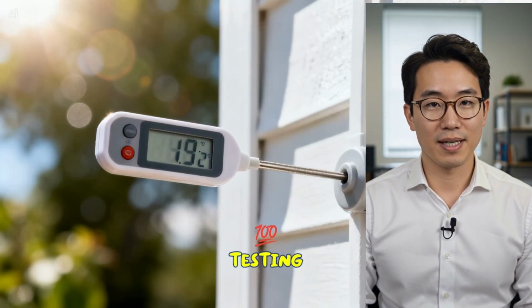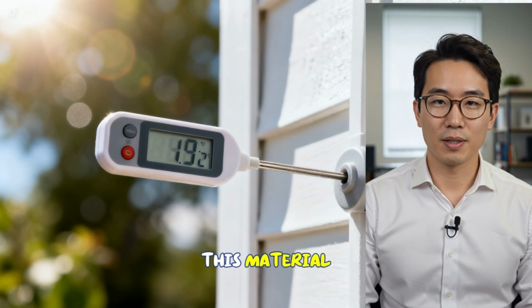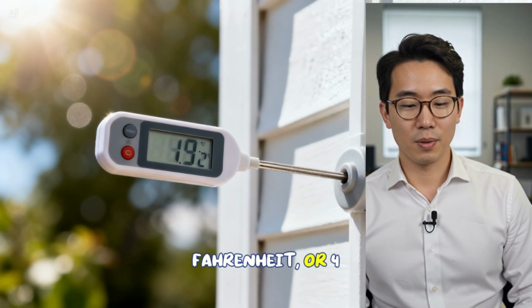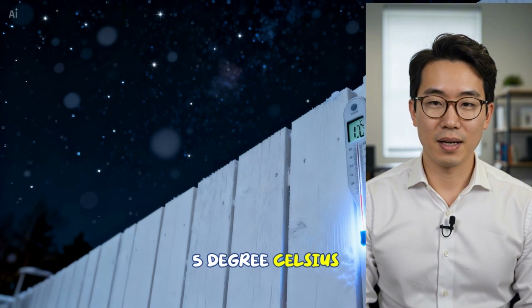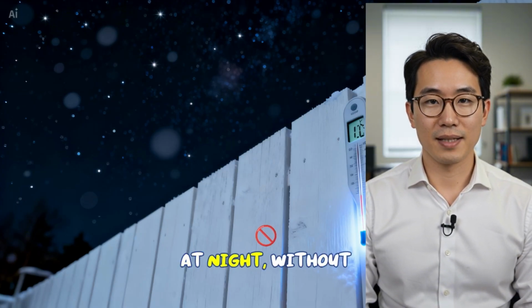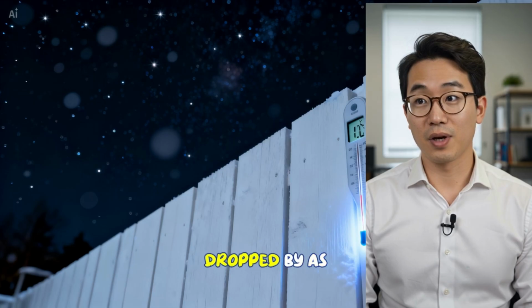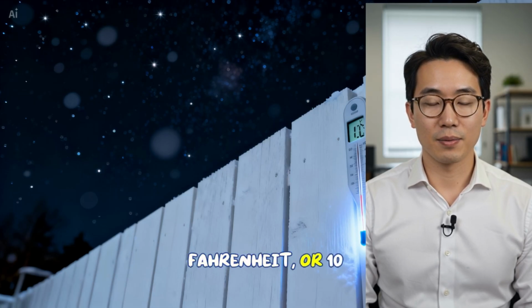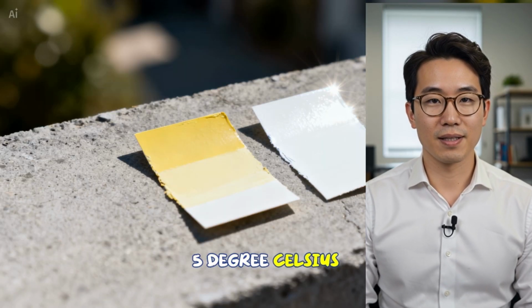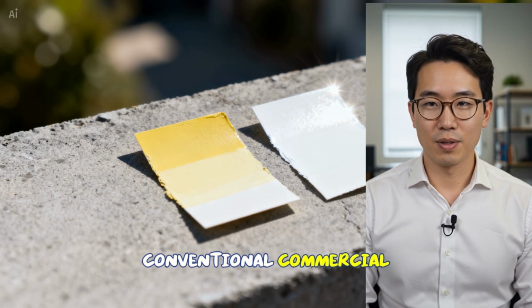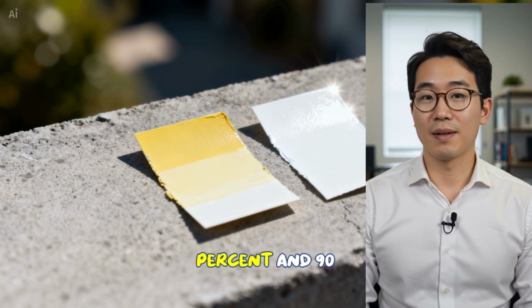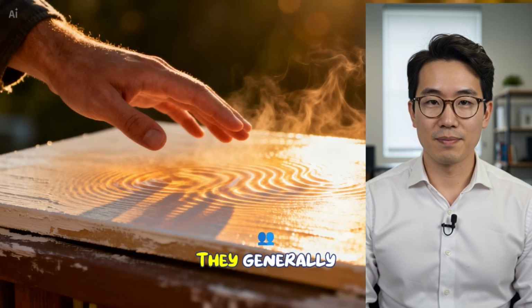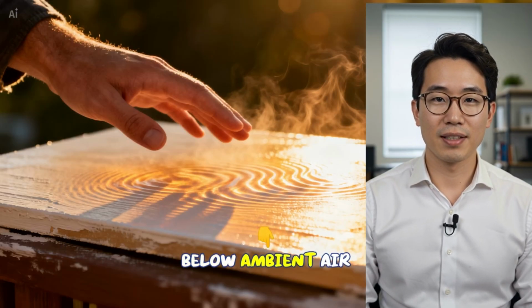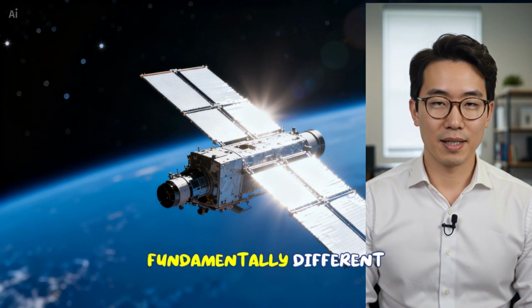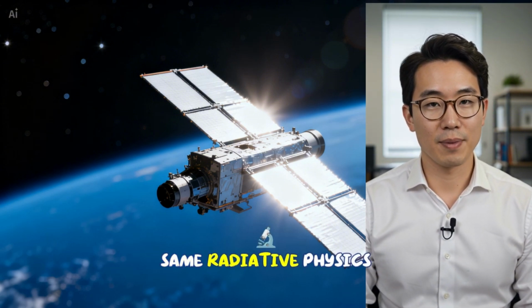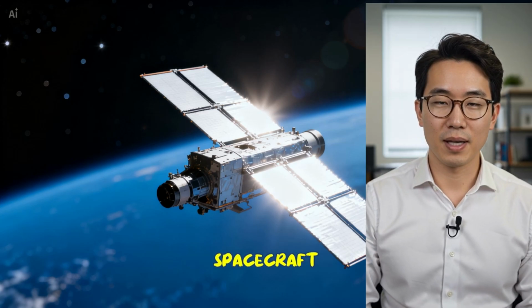In controlled sunlight testing, surfaces coated with this material reach temperatures about 8 degrees Fahrenheit, or 5 degrees Celsius, below ambient air conditions. At night, without solar input, the same surfaces drop by as much as 19 degrees Fahrenheit, or 10 degrees Celsius, below surrounding air. Conventional commercial white paints typically reflect between 80% and 90% of sunlight. They generally do not produce temperatures below ambient air at all. This represents a fundamentally different performance range, built on the same radiative physics principles used in spacecraft thermal control systems in orbit.